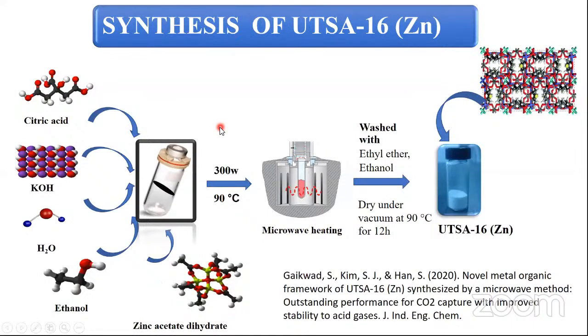Another MOF we developed by using the same technique, the microwave method, is UTSA 16 zinc. We replaced the metal precursor cobalt acetate by zinc acetate dihydrate. Ligand, solvent, and the other reaction mixture, everything we kept the same, and we used the same reaction conditions. So we developed a new novel MOF, UTSA 16 zinc, and we also used this material for CO2 absorption.